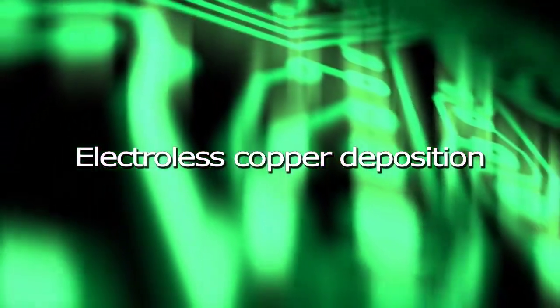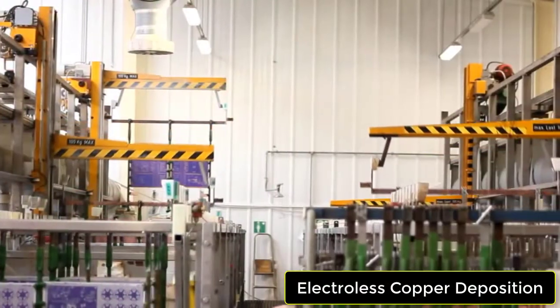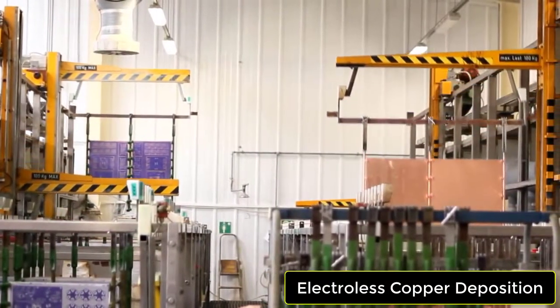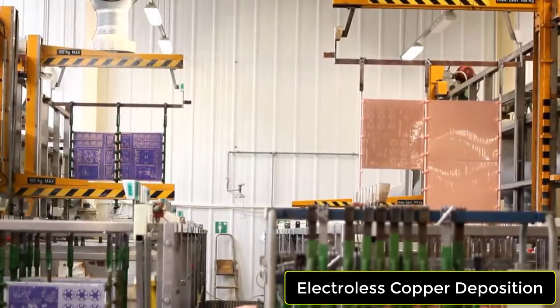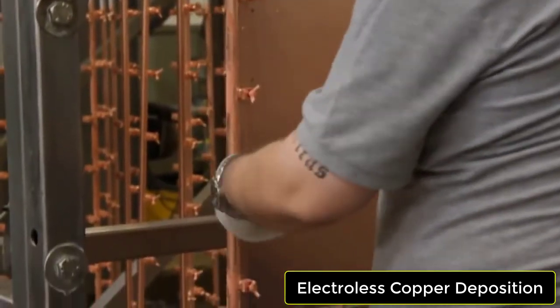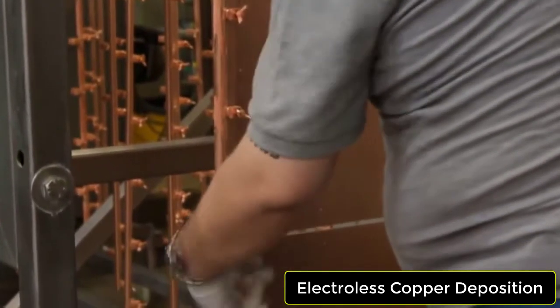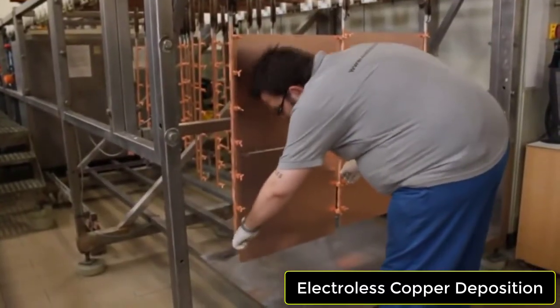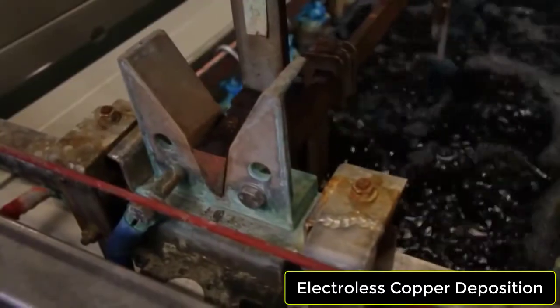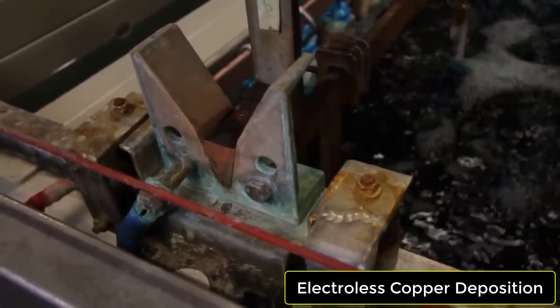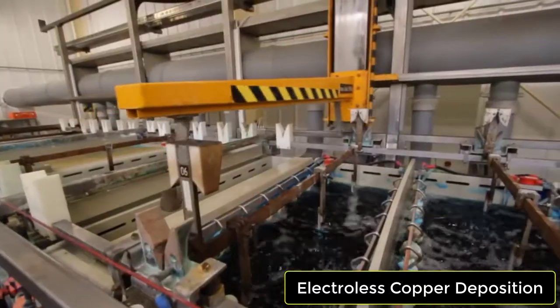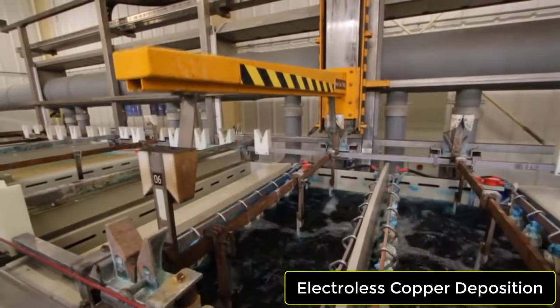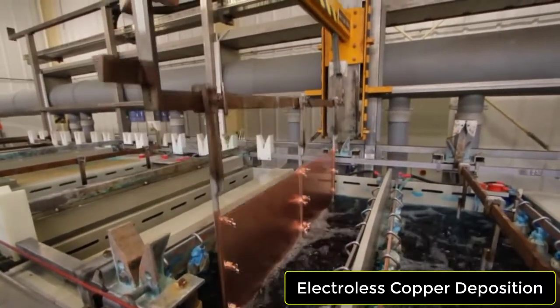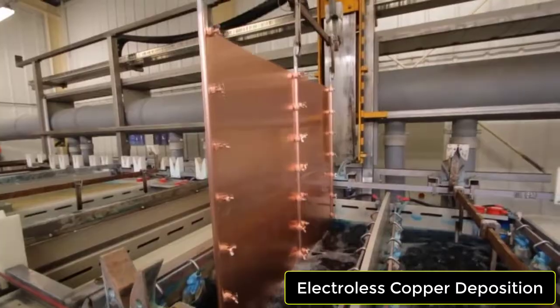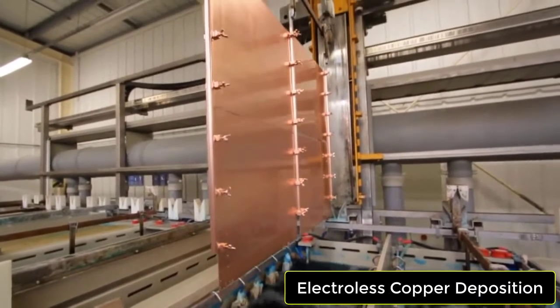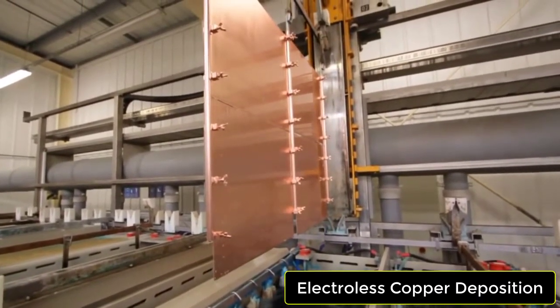Electroless copper deposition. The first step in the plating process is the chemical deposition of a very thin layer of copper on the hole walls. The operator clamps the production panels into the jigs. The line is fully computer controlled and the panels are carried through a series of chemical and rinsing baths by the overhead crane. Almost all PCBs with 2 or more copper layers use plated through holes to connect the conductors between the layers. A good connection needs about 25 microns of copper on the walls of the holes.